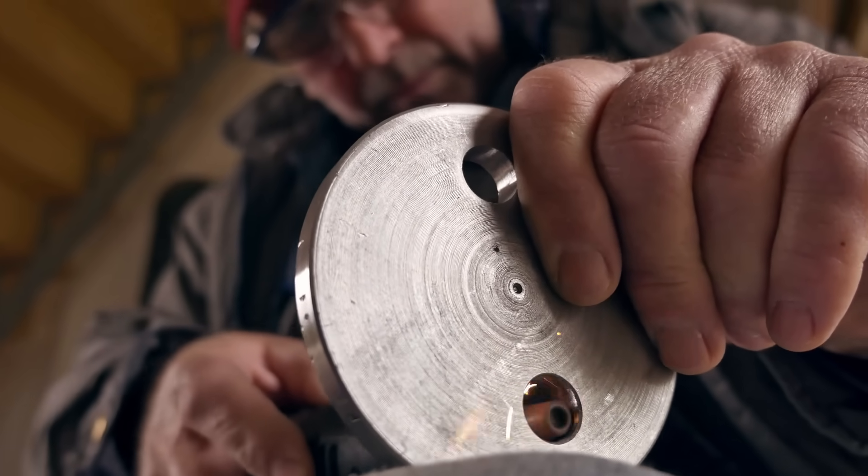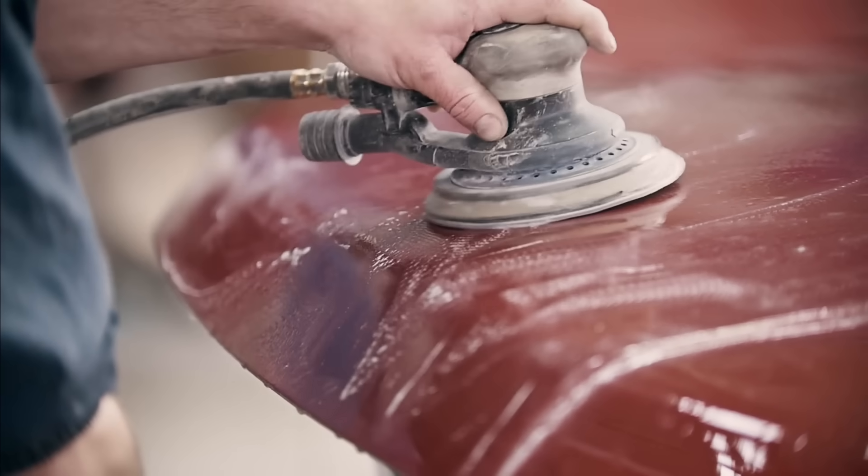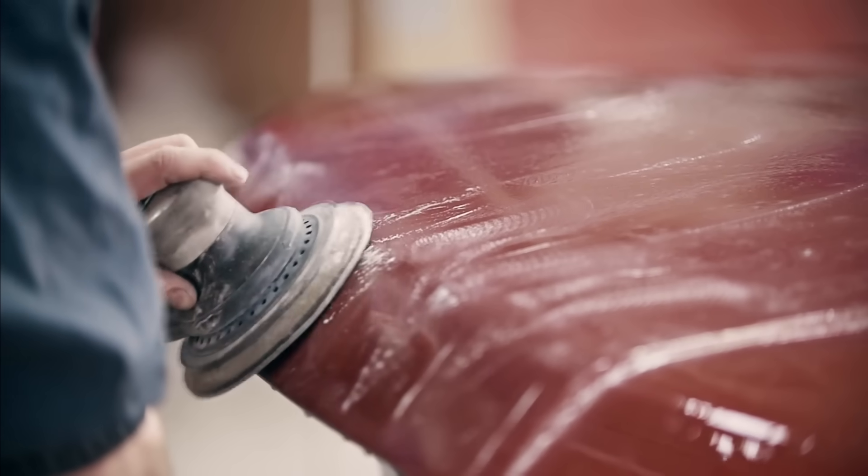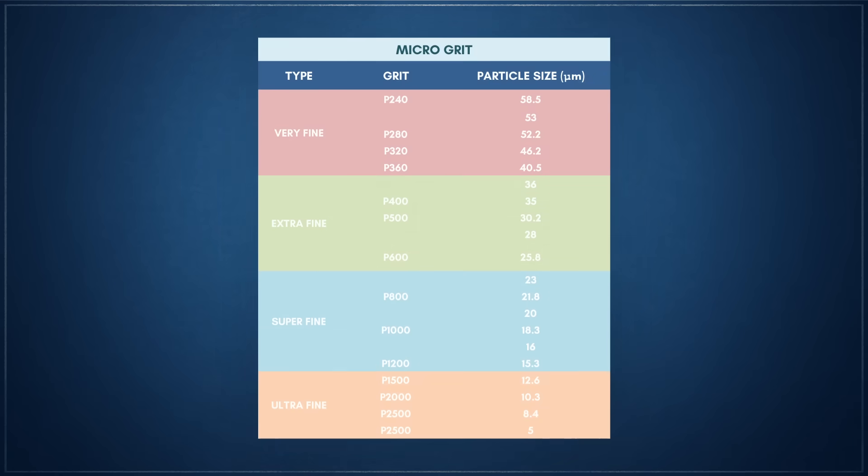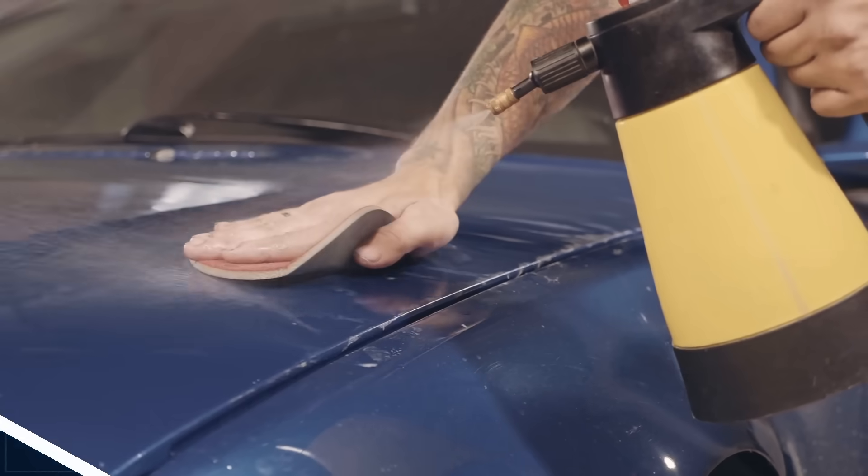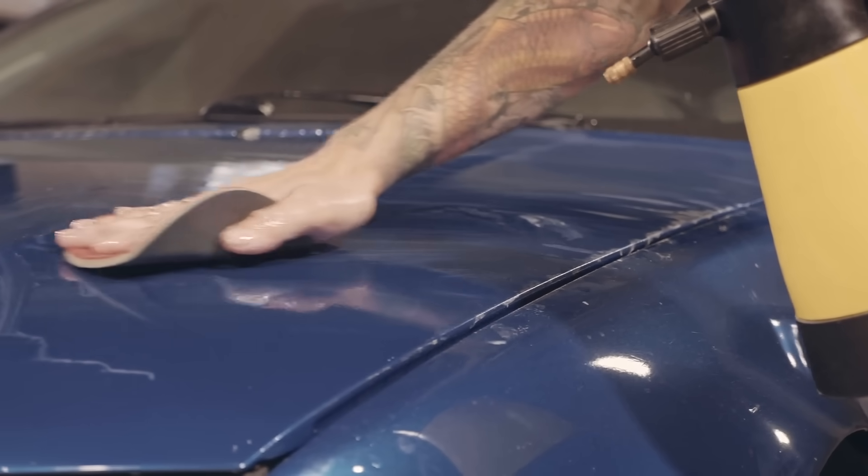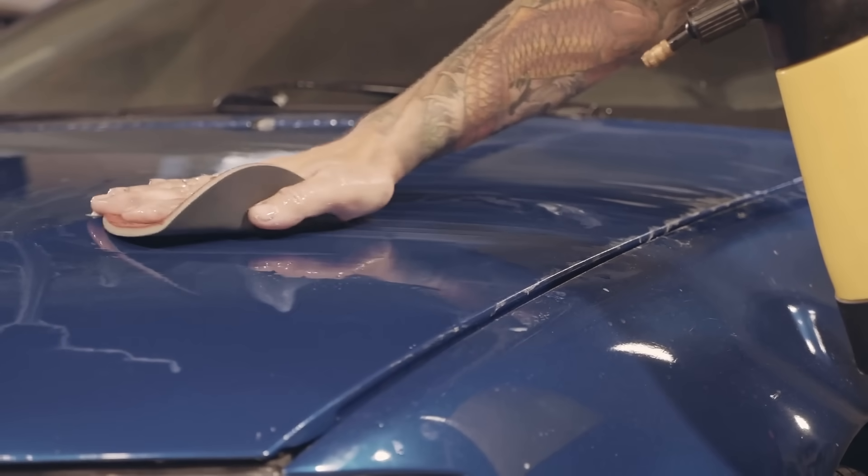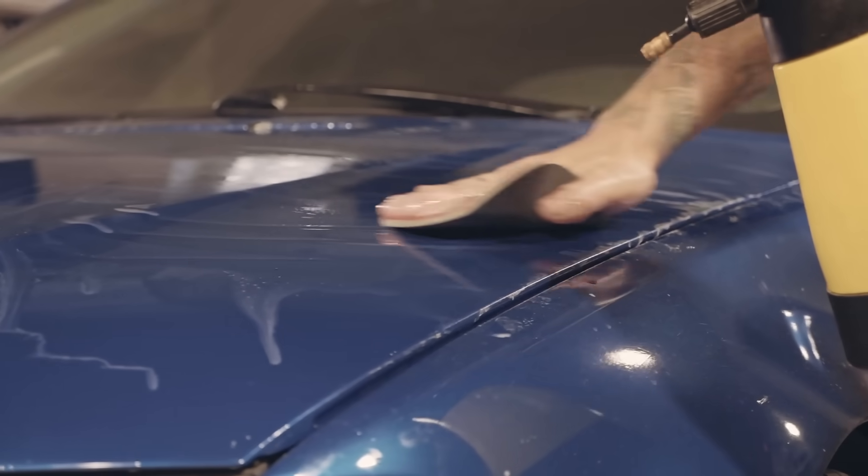Micro-grit products, in contrast, tend to use mostly finer, traditional fused abrasives, with silicon carbide being a popular wet-dry option at the higher grits. They range in designation from P240 all the way up to P5000, with grain sizes ranging from 60 microns down to just 5 microns. Micro-grit products are targeted more towards surface refinishing and polishing. They're designed to have more consistent and controllable abrading properties, focusing more on the surface finish they produce than material removal.